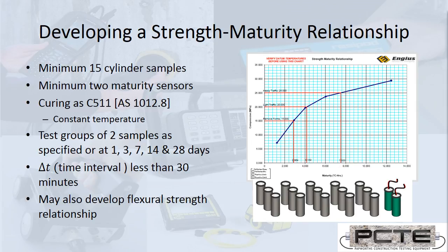One of the critical things is these samples are cured as per a normal concrete sample. Maturity is a way to create a relationship based upon conventional curing environments. So that's 28 days, 23 degrees in lime water with 18 hours air curing first. Critical things, the instrumented samples must be cured the same way the concrete samples are. If they get colder or hotter than the samples that are going to be broken, they will no longer represent the maturity of those samples. So it's important that every mold be moved together at the same time as soon as possible.